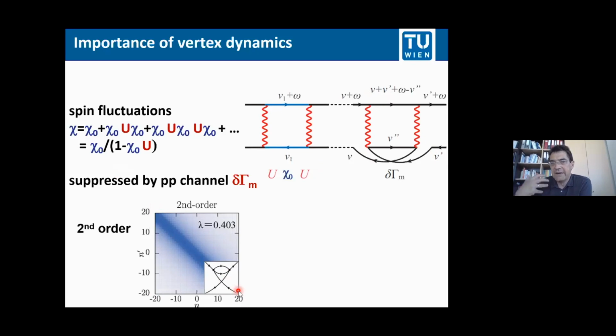And this way, with this dynamics, even on the local level, calculating this coupling vertex in an impurity model, you can already describe this very suppression. And that's also why we think that if particle-particle diagrams become more important, or the non-local contributions, if we approach the superconducting regime, this will go in the same direction and somewhat suppress superconductivity.